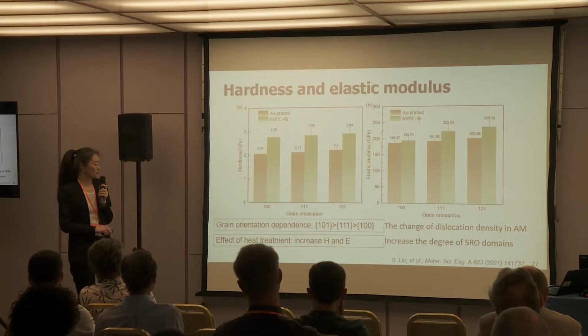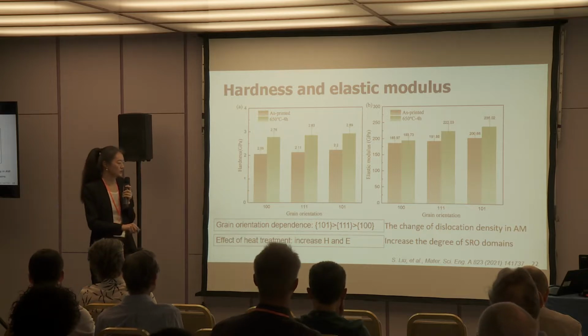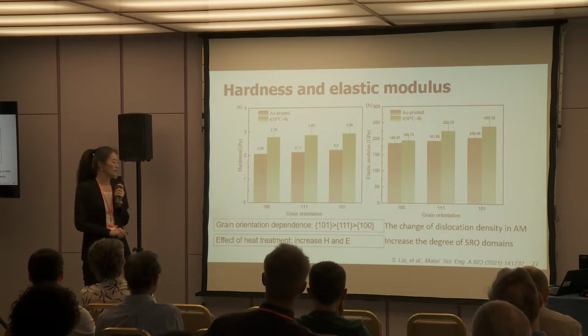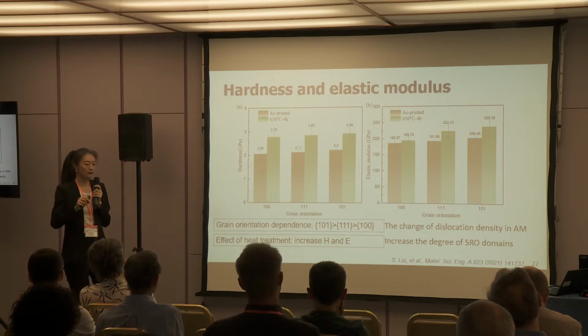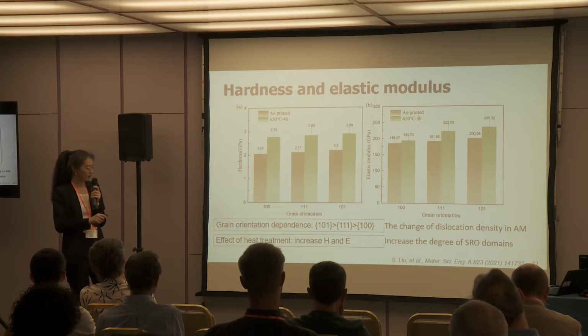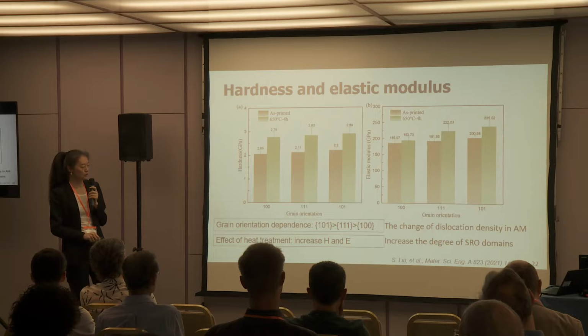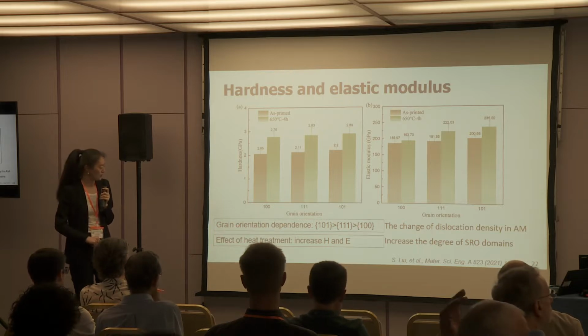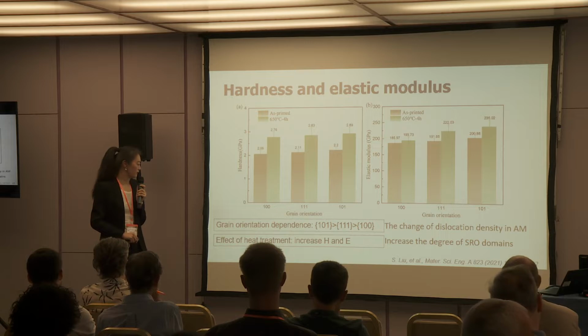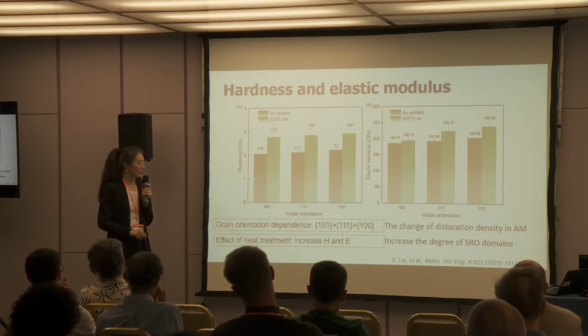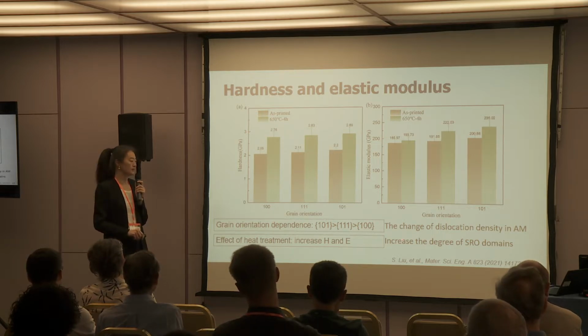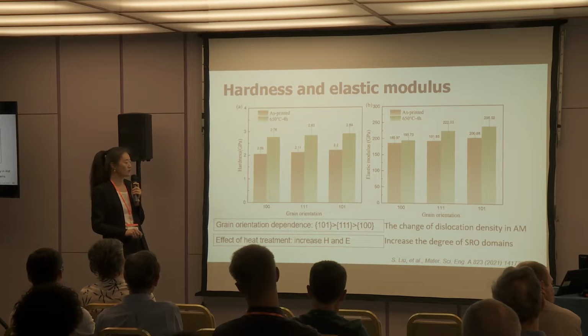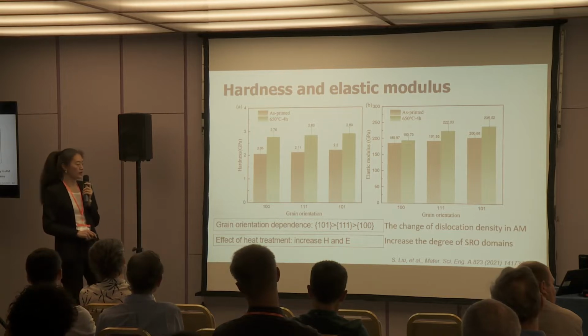We attribute this grain orientation dependence to the change of the dislocation density in the material, as different grain orientations have slightly different dislocation density. But we are lacking transmission electron microscope verification for this part, so it's ongoing now. And the heat treatment effect is actually attributed to the increased degree of short-range order domains in the high entropy alloy.